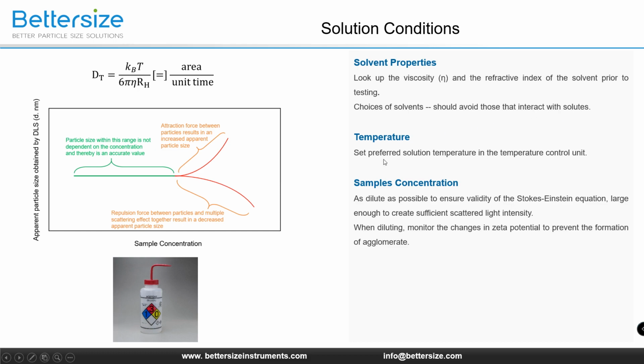If the samples are polyelectrolytes that possess Coulomb interactions between particles, the scattered light intensity might be influenced. To disturb the potential Coulomb interactions, add an adequate amount of salt into solutions without changing the solvent's refractive index.